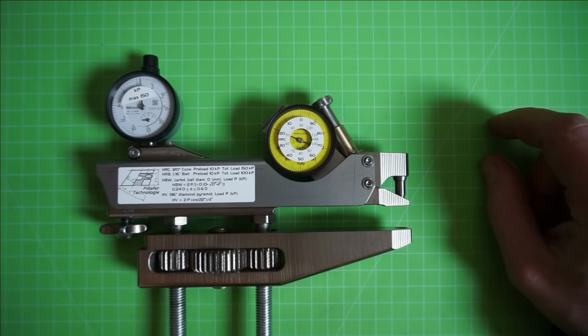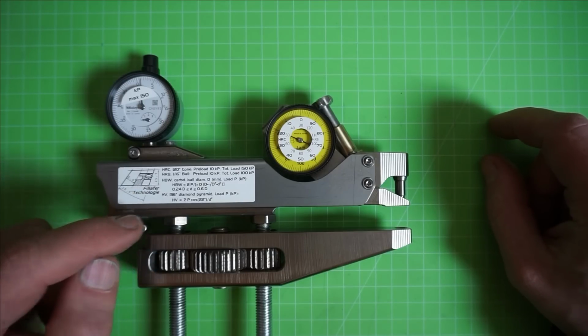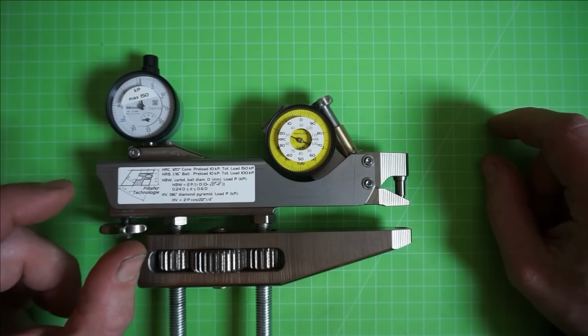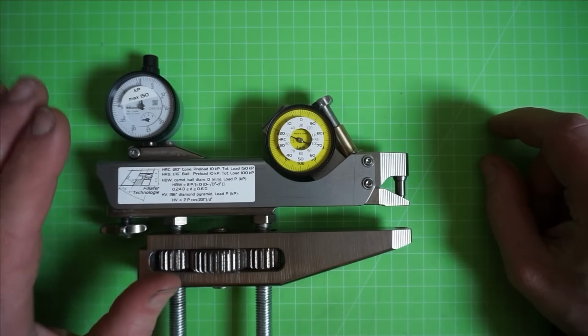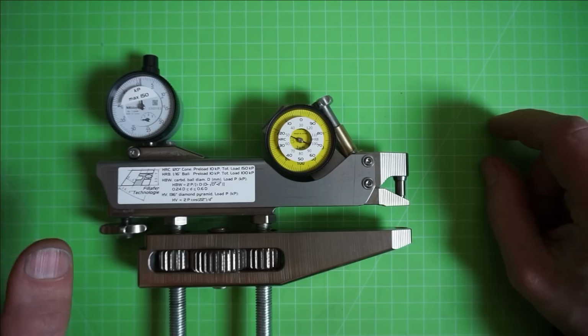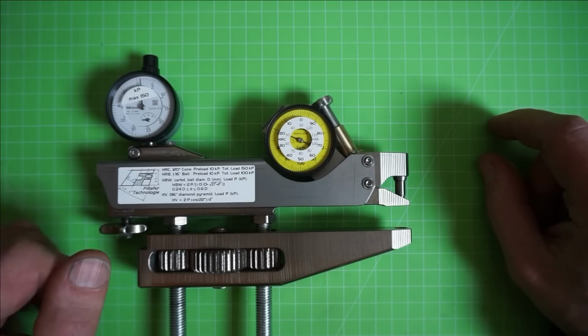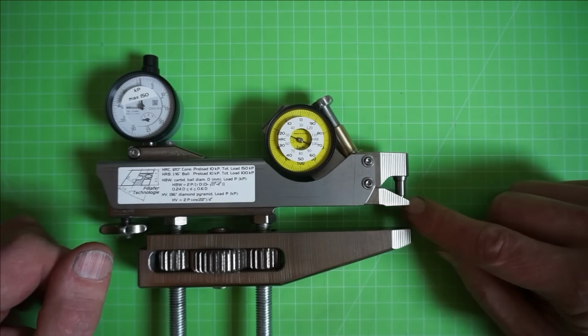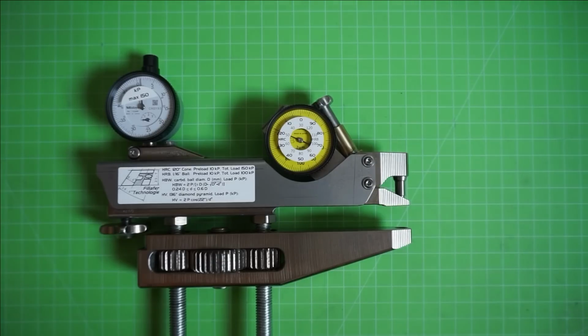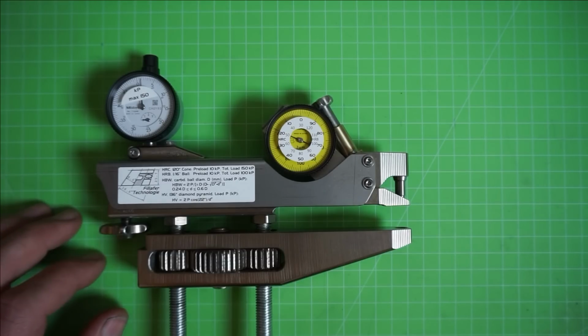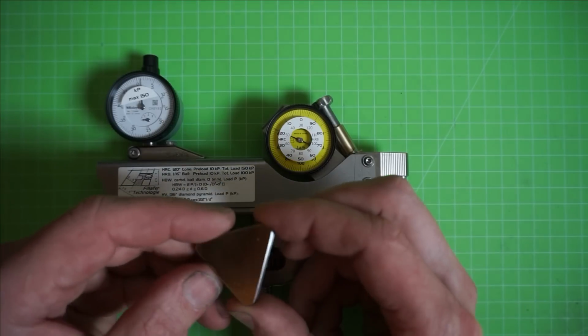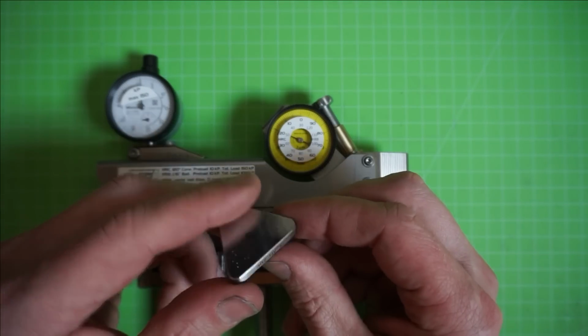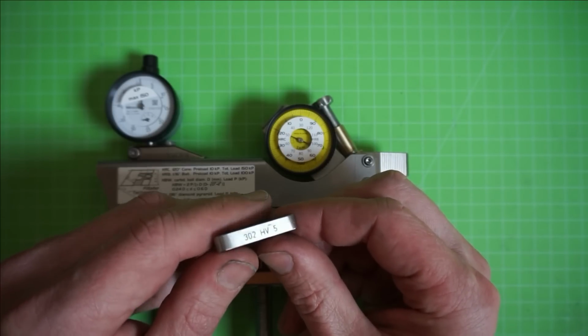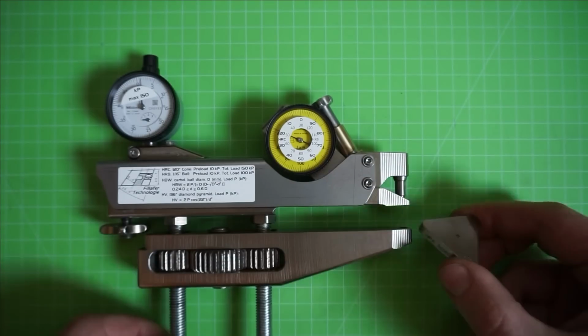But if you have only very shallow indents, then the edges that highlight the indent, which you have to measure to get the size of the indent, are very hard to see. With Vickers, that's not a problem. It's always a square, and that's why Vickers is the most versatile hardness testing method, because it has the least disadvantages in comparison to the other methods. So let's use this Vickers comparison plate here. This one has a 302 Vickers hardness.